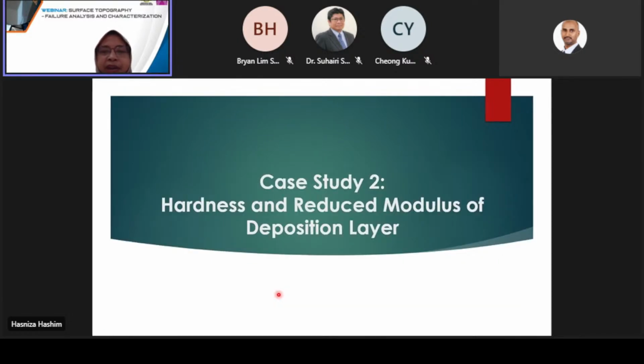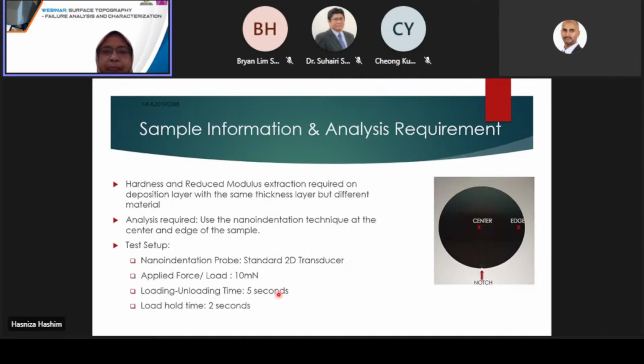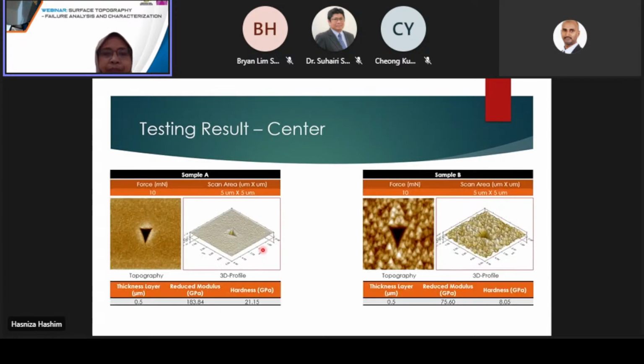For the next case, the hardness and reduced modulus of the deposition layer at different thickness layer. I'm sorry, the objective is to get the hardness and reduced modulus on the deposition layer with the same thickness but different material. It also used the nanoindentation technique at the center and edge of the sample, also using the standard 2D transducer. We also apply up to 10 millinewton with the loading and unloading time of 5 seconds and hold time of 2 seconds. From this in situ imaging, we can see that there are two types of material surface that can be observed through the in situ imaging technique.